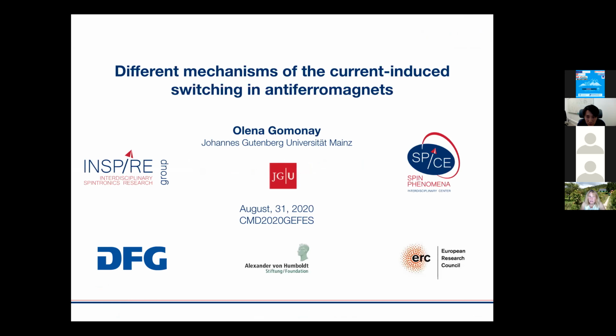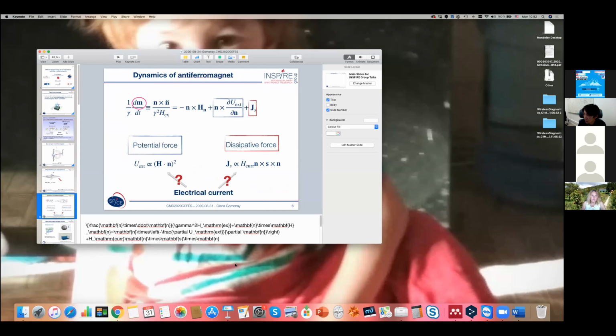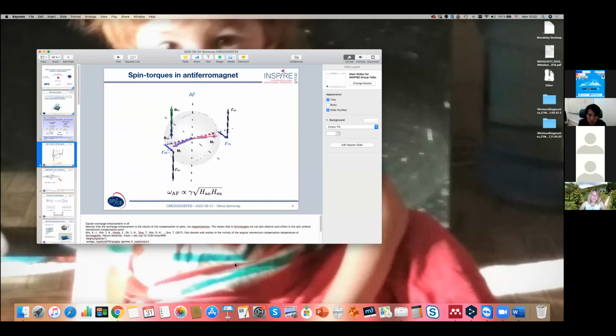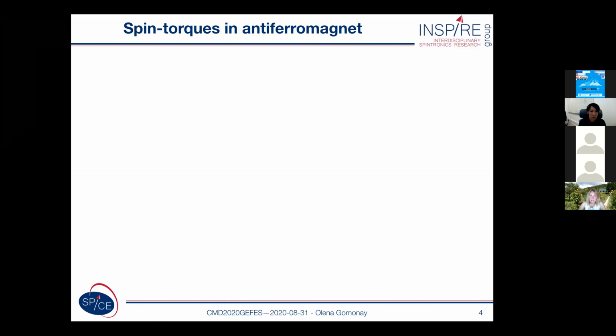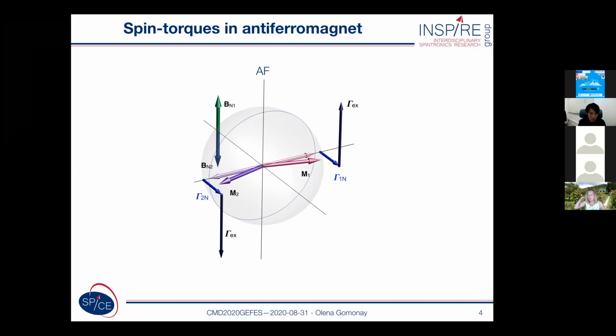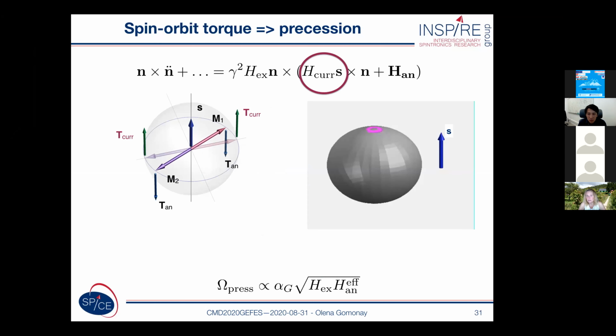No. This is the main point of all this antiferromagnetic dynamics: in order to have dynamics, you need to induce canting of magnetic sublattices. Effectively, this canting is extremely small, and because it's small, this allows us to exclude the magnetization from the equation of motion. So we can get these effective equations in terms of the Néel vector. But you cannot exclude the magnetization fully, because otherwise the system will not rotate at all.